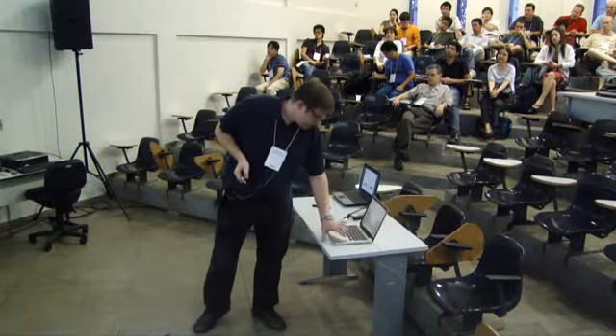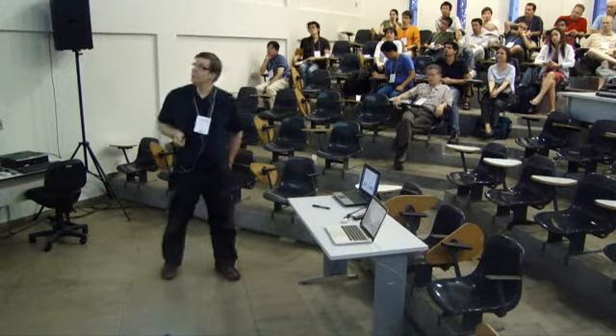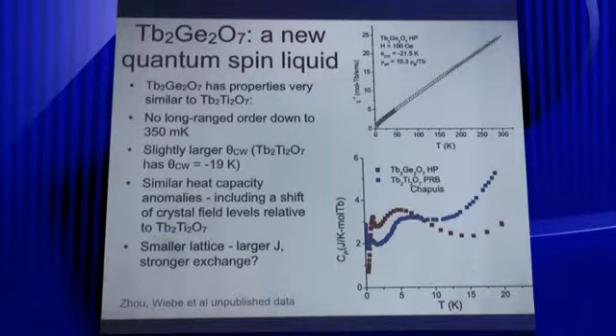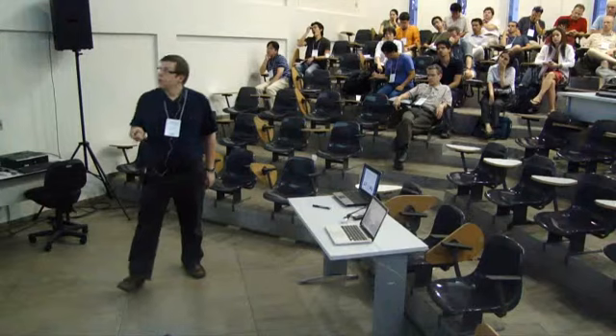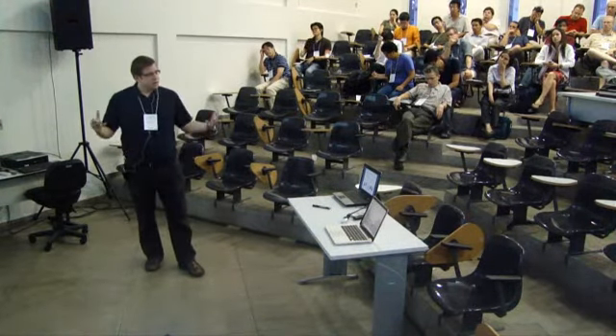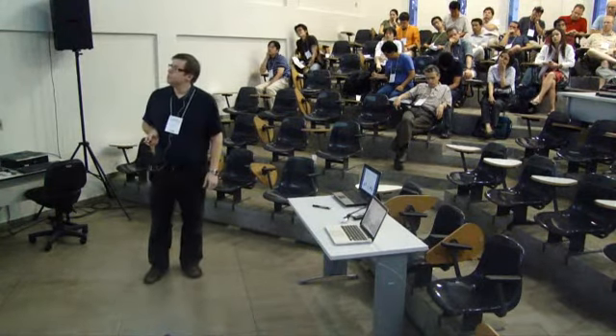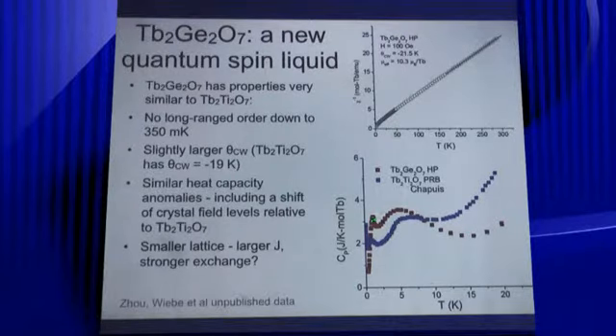So if you really want to look for monopoles, it's in these compounds compared to the canonical titanate compounds. Because there's some interest in terbium titanate, I thought I'd mention some data on terbium germanate. It has properties very similar to terbium titanate. You look at the Curie-Weiss susceptibility, and get a Curie-Weiss temperature of roughly minus 21 compared to minus 19 in terbium titanate. And of course, there are crystal field effects in here, but you can naively understand this as the lattice is smaller, so there's a larger J, so there are stronger spin-spin interactions. And if you look at the heat capacity at low temperatures as compared to a PRB paper, it does look very similar. So you expect that the low temperature magnetic properties are probably similar to terbium titanate, although we don't have enough sample to do neutron scattering. We only have on the order of milligrams of this so far. But everything is shifted, right?